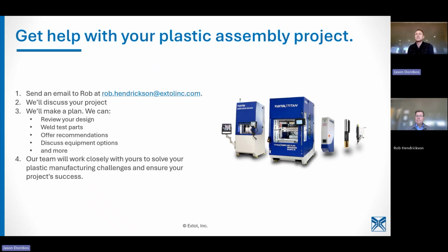It really actually comes down to how flat or how close to flat your parts are. If there's a lot of variation in the flatness of your parts, we can pull some of that warp out with tooling. We hold those parts flat and we hold them into the tooling tightly. But if there's still some inconsistencies because of sink or knit lines on the surface, we want to melt those away. So if there's a lot of those, then we might have to melt a little bit more.